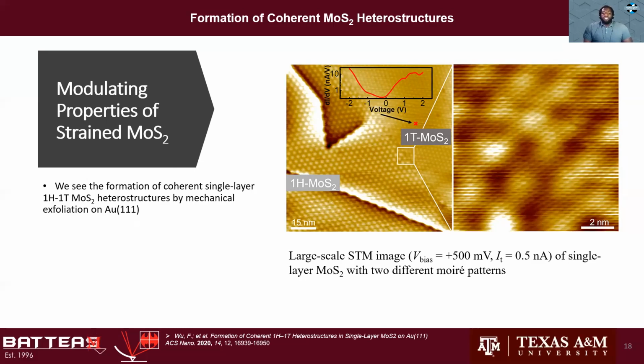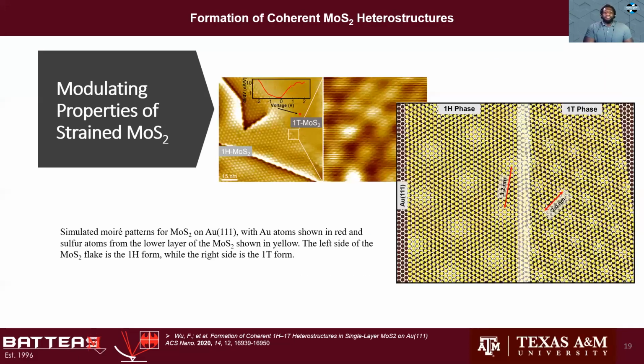And we use scanning tunneling spectroscopy to confirm the presence of the two phases and computational models to replicate the moire patterns of the two phases. Here we see that the periodicity and structure of the simulated patterns are similar to those observed in the scanning tunneling microscopy image. In addition, the rotational angle between the two moire patterns closely matches our experimental STM data. We believe that this formation is likely due to charge transfer between the metal substrate and also built-in tensile strain in MoS2 during the transfer.